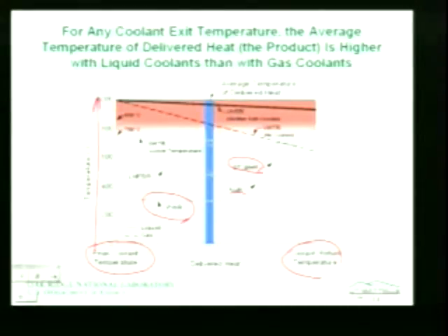Let's say we want to have output of a reactor at 1,000 degrees C. If we have a liquid coolant at 1,000 degrees C, like our molten salt reactor, the average temperature of the heat dumped from the reactor to the power cycle will be about 950 C. So we get almost all of the heat delivered at high temperatures. If we have a gas-cooled reactor with the same exact exit temperature, we find the average temperature of the delivered heat is a little over 800 degrees C.